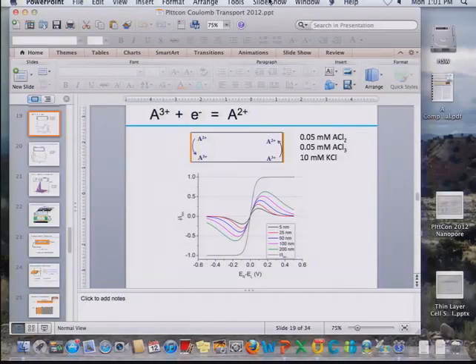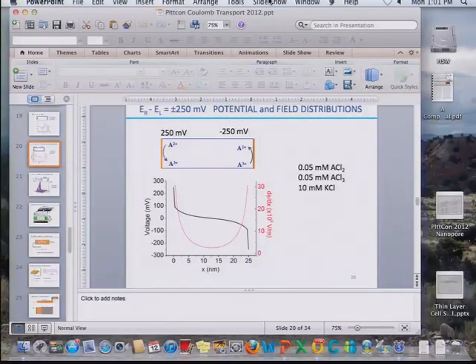Actually, I've got a few more calculations here for this redox couple, 3+/2+, in a cell. Here's the current-voltage curve you expect for electrodes far apart. And then as you push them together, this is 200 nanometers down to 5 nanometers, what you see are these odd-shaped curves. And as you go to high potentials, either positive or negative, the current goes to 0. So why does the current go to 0 here? Well, first of all, we'll look at the potential and electric field distribution. Here's the electrical potential. Here's the field. The fields are very high, but they're not off-scale high. They're typical of what you would expect for an electrical double layer.